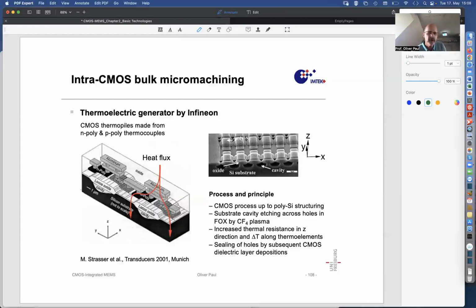So if I have here a temperature T0, and here also T0, and here I have T1 larger than T0, so here is T1, then this contact and this contact are hotter than these contacts here. And therefore, if I measured a voltage difference between here and here, a delta V, I would measure a delta V proportional to delta T with what proportionality constant? With the Seebeck coefficient between the N and the P doped polysilicon. This is how thermocouples work.